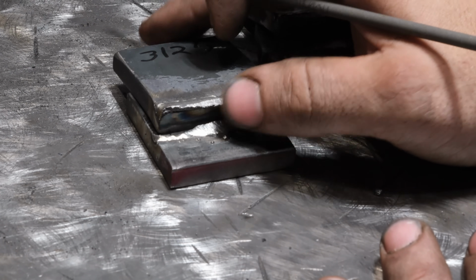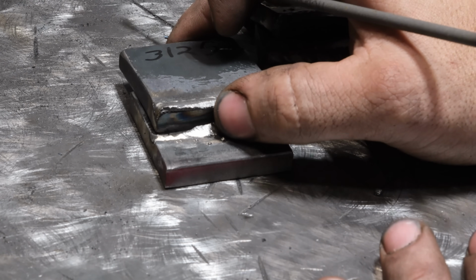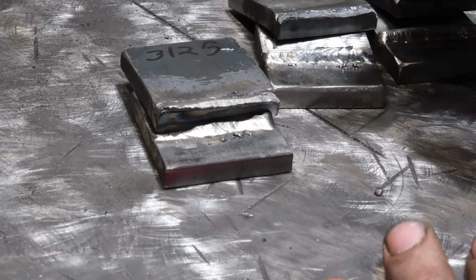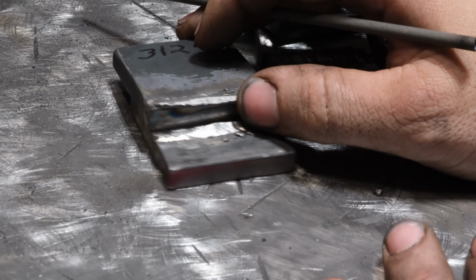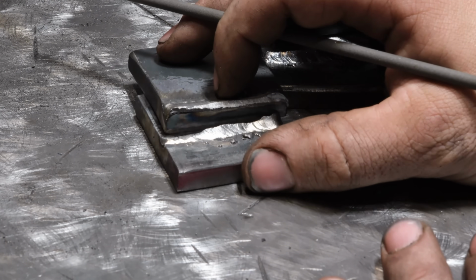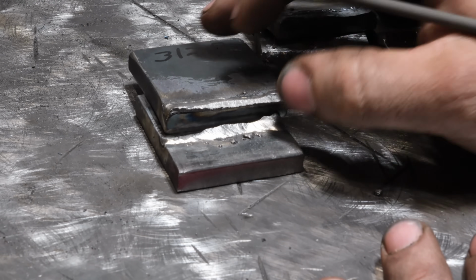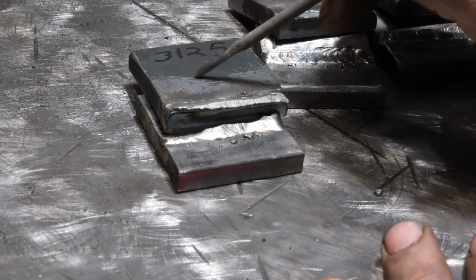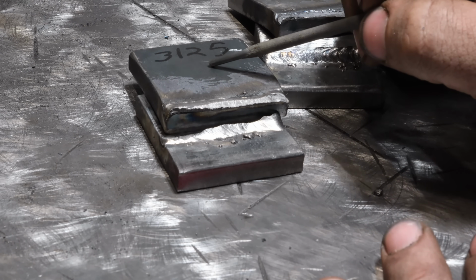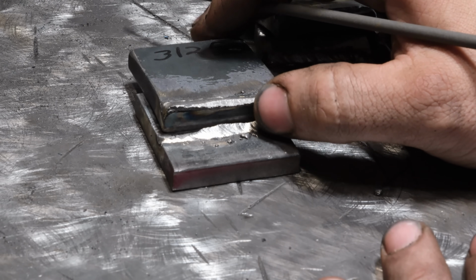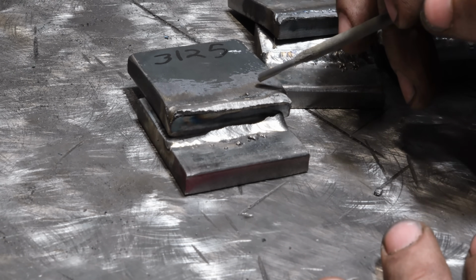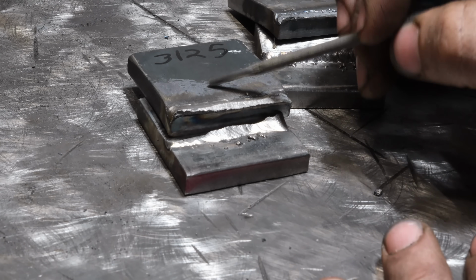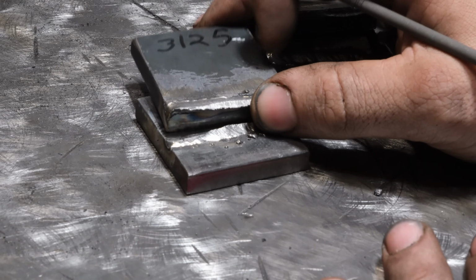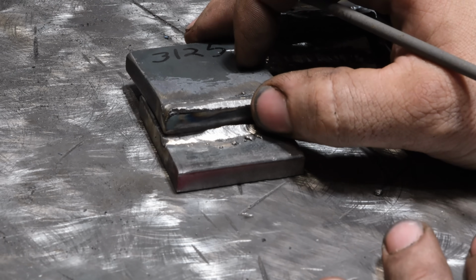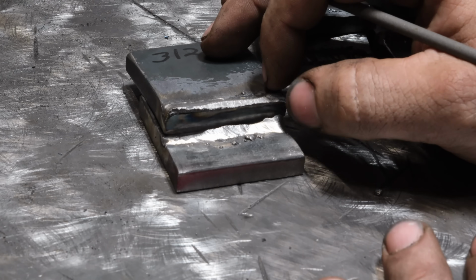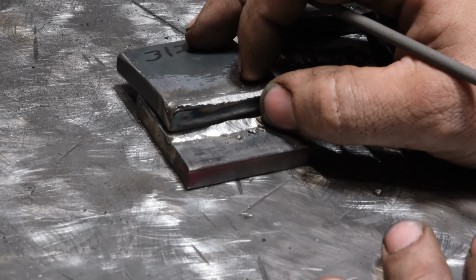So realistically, 312 is not something you should be welding mild steel together with, especially thick plate, unless it's all you have. Now, keep in mind, guys, 312 stainless is an awesome tool for your toolkit, because if you were to run into high carbon steel or castings or any number of things, anvils, leaf springs, you can weld them successfully with 312 stainless. Now, I'm not saying that you should go and put 10,000 pounds in the bed of your pickup truck after running a pass on the leaf spring in the back with this, but you would be able to get out of the mountains of Afghanistan with this. So to put it in perspective, in an emergency, awesome life-saving tool, but you don't want to make a habit of using this to build stuff, especially over 7018.